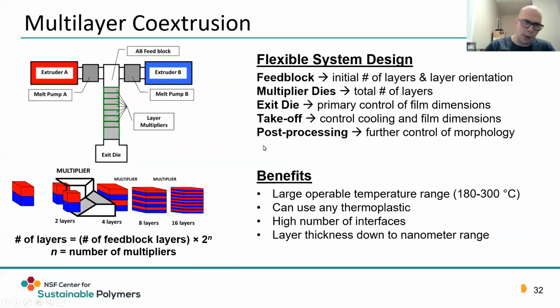Another step up from that, if you're looking for a higher number of layers or interfaces, is multi-layer co-extrusion. This is a much larger scale, needing about 500 grams per extruder, with a fair amount of flexibility beyond that. You can control your number of layers from the onset at the feed block with the addition of layer multipliers, and control your film size and thickness with your takeoff, exit die, and any other post-processing of interest.